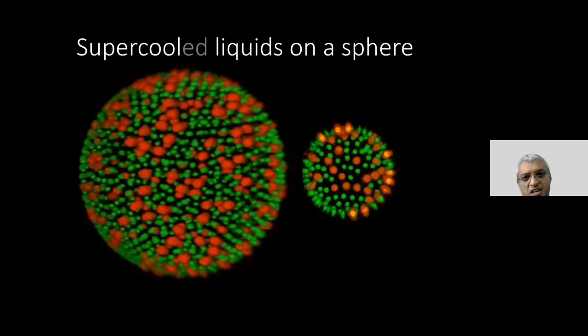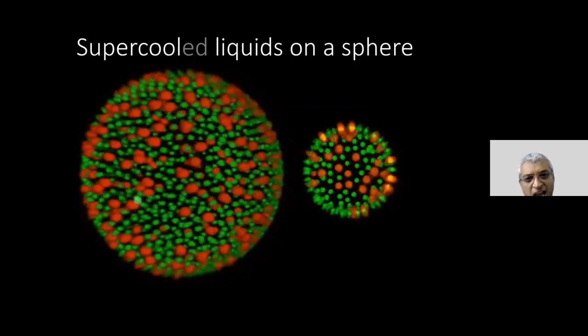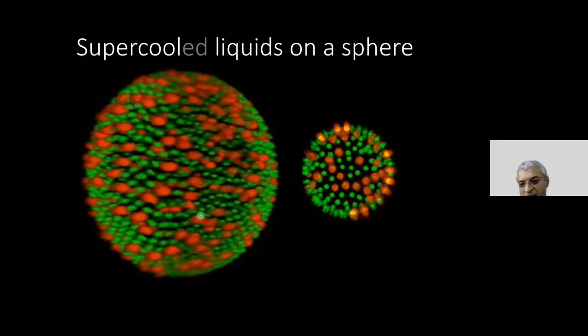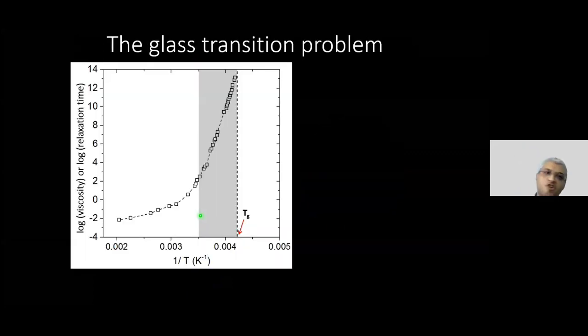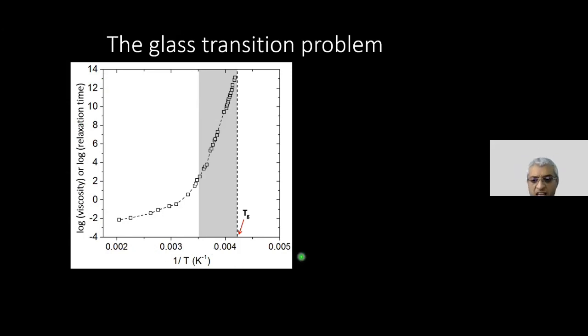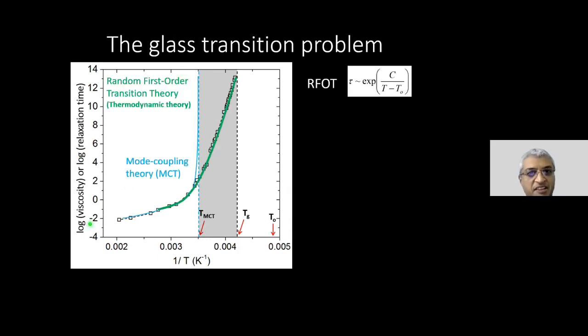Navneet has been doing. The idea is to basically look at what happens to liquids on the surface of a sphere. And going back to the favorite plot of mine, I'm plotting for you the log of viscosity or the log of relaxation time as a function of 1 over temperature. Now, we basically were talking about how a glass can still crystallize, but then there is something very fascinating about this plot, okay?